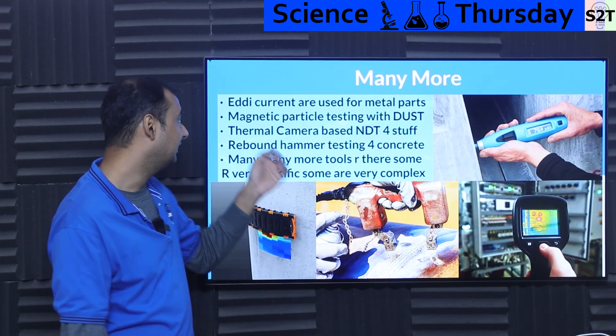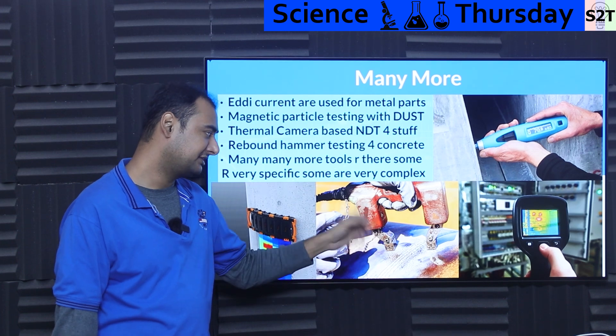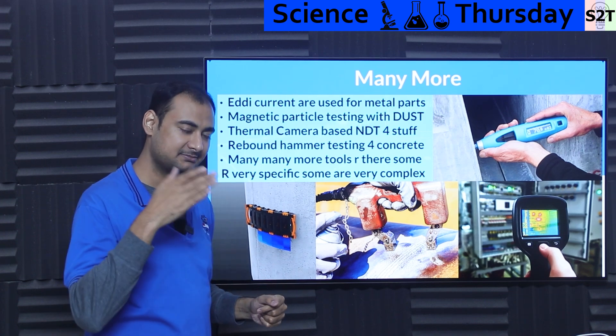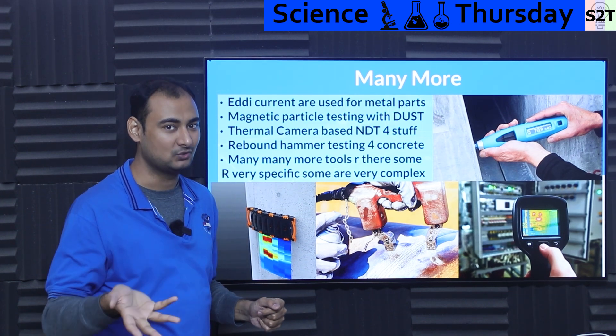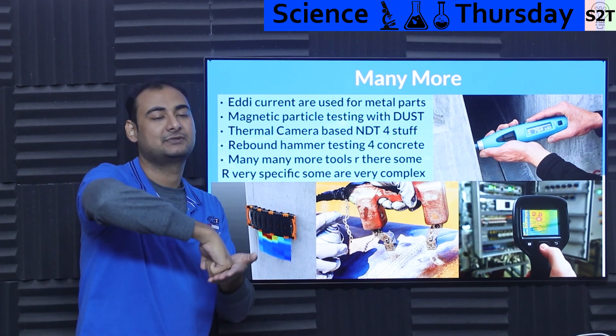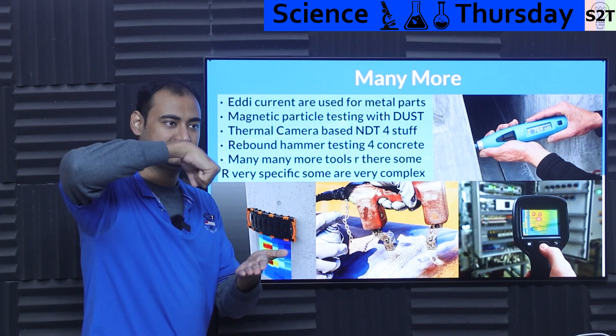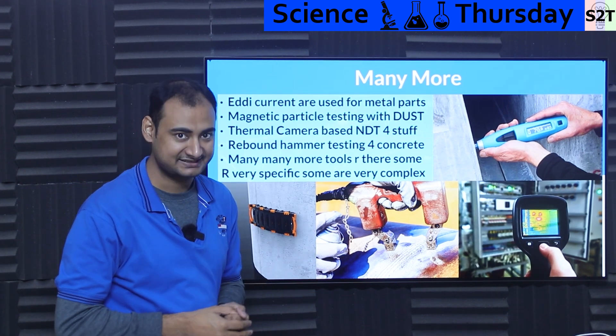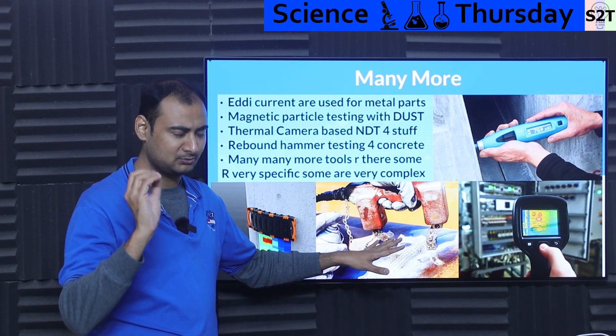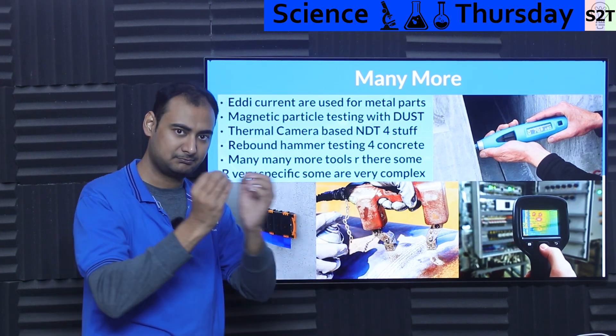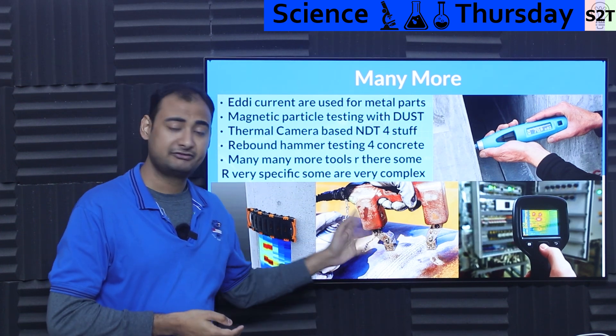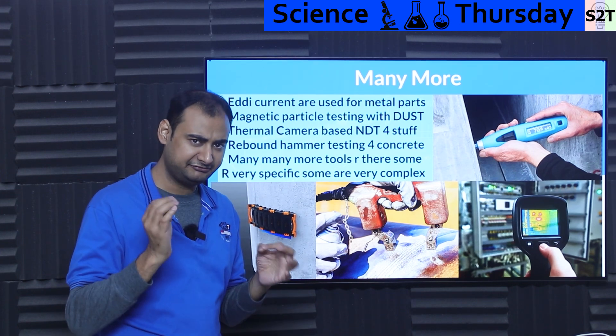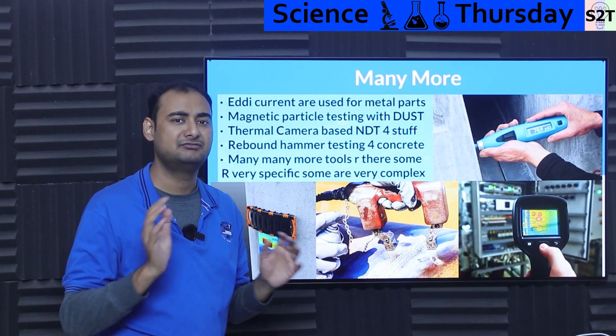A few popular ones include eddy current systems. Eddy current is generally not always preferred because if a crack is perfectly aligned to the magnetic flux, it will not show up. That's why technicians are trained to scan on one axis and then another axis, so flux alignment does not mask any issue. Another method involves iron filings of very small specific particle size — they clump up and show you where a fault is.